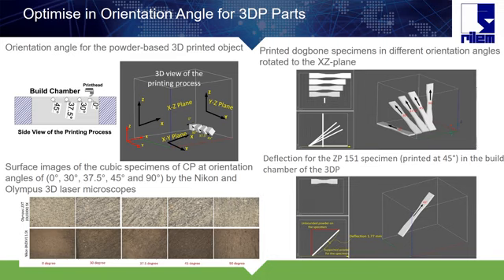Furthermore, it is necessary to know that the highest compressive strength was obtained at 0 degree rotation in the XY plane, and for shear strength we got a very good result at a 45 degree orientation angle. So that means that's the optimum for us. For tensile and flexural strength, at a 0 degree orientation we got the highest value, and therefore those angles need to be considered for our printed parts. Overall, 0 degree is a very good angle to print our specimens. However, from the perspective of each material, these angles may be different, and the purpose may also affect the results, depending on what we use it for.